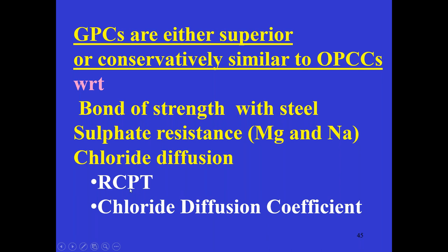Some RCPT tests were done for OPC and they connected that. What is the chloride diffusion value and this charge passed, and they connected. So that connection is not done for other concrete. That's why it's never a parameter for any other concrete. Even then, we found it is slightly lower than ordinary concrete. Okay. It is because it is an electrical conductivity test basically.